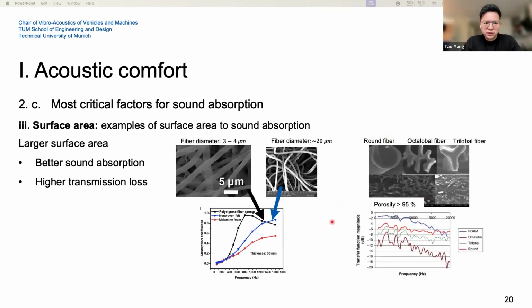Here are two examples to see how surface area affects the sound absorption. In this image, the fiber diameter is around 3 to 4 micrometers. In the other one, the fiber diameter is around 20 micrometers, but they have the same thickness. If the fiber is thinner or smaller, it always means it has a larger surface area. So the black one represents the sound absorption of the fiber diameter around 3 to 4 micrometers. Then the blue line, you can see it is much better than the regular fibers.